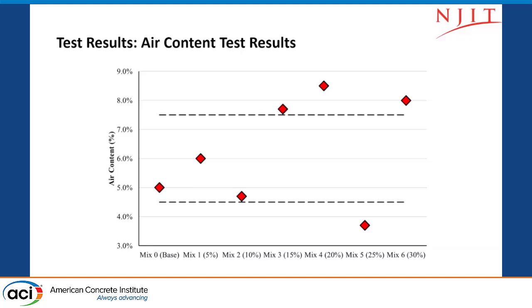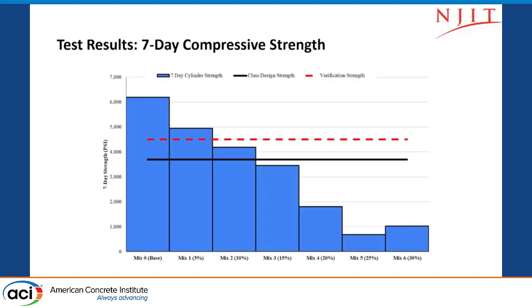So we have a couple of anomalous points here, those are the bottom points, but we put them in case. So here, the 7 days compressive strength, and as we can see, the solid black line is the design compressive strength for NJDOT, and the dotted line is the verification strength. So this is the 7-day compressive strength in PSI, pounds per square inch, and those are the replacements until 30%.